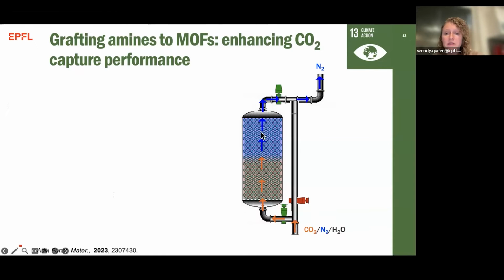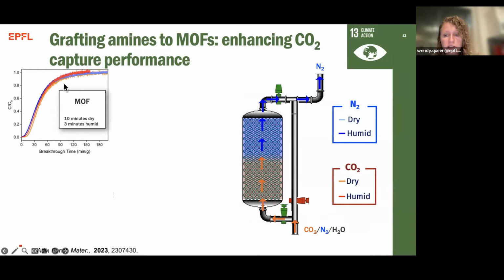in humidity. So what happens is that our adsorbent will adsorb the CO2. The nitrogen will pass through and we'll see it break through the column first, okay? When the CO2 breaks through, this means that our adsorbent is effectively saturated. And so here what you're seeing are the breakthrough curves associated with the MOF in dry and humid conditions. And what you'll note is that under dry conditions, the separation time for nitrogen and CO2 is about 10 minutes. Under humid conditions, that decreases significantly because the water is competing with the CO2 for bonding sites.